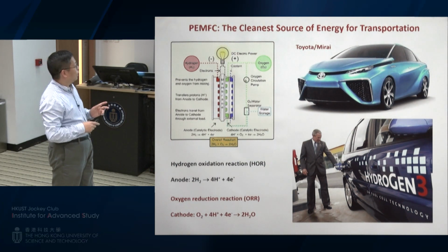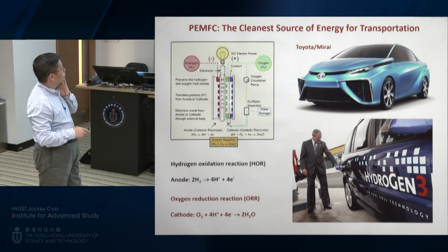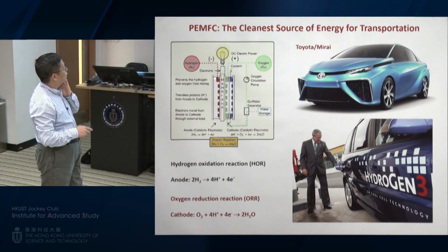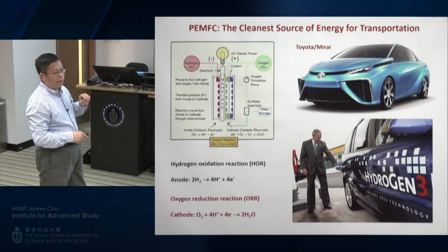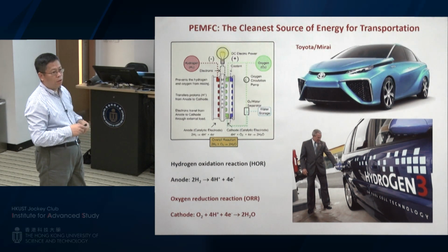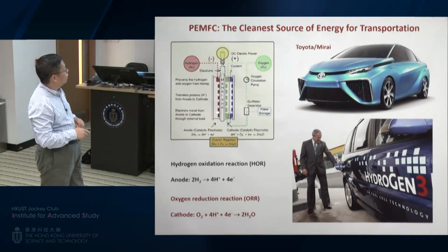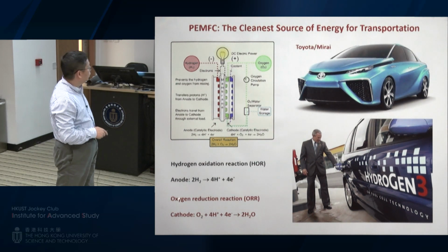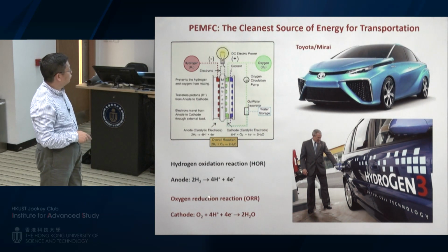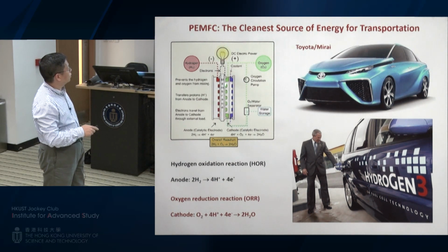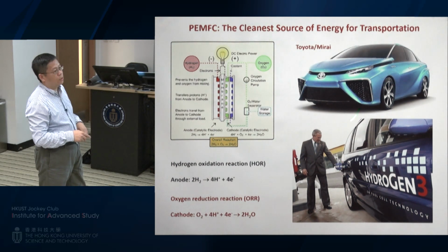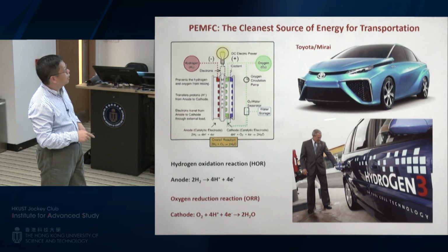Now of course, one of the issues as I mentioned is the cost, because for these devices to be useful, you have to add a catalyst to the surface. Otherwise, this reaction will be too slow, and you can only generate a very, very low current density that won't be able to drive any device. So that's why you need to add a catalyst to speed up these reactions. In particular, for the oxygen reduction reaction on the cathode, you have to add a lot of catalyst. This catalyst contributes a lot to the cost of the fuel cell device, and also the vehicles, of course.